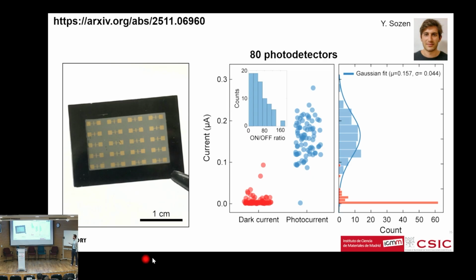So we fabricated 80 photodetectors. If I remember correctly, this is tungsten diselenide. And basically, out of the 80 photodetectors, there was just one that didn't work. Okay, so not bad. I mean, almost 99% success yield. And of course, we have a dispersion in the photocurrent and so on, but it's expected from this kind of network of interconnected flakes nature of the films.